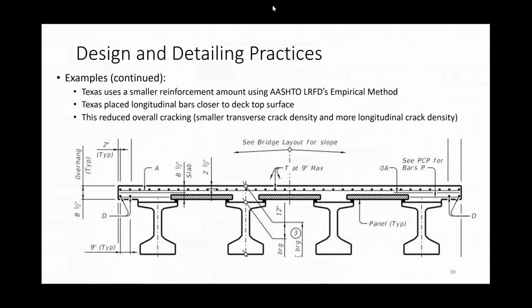All right, and then next up, Texas DOT again discussed how they reduced the amount of reinforcement as a method to reduce cracking. And that may sound counterintuitive, but their reasoning here is that if you have a smaller reinforcement amount, the corrosion products that build over time are going to be small, and that's going to create less pressure when they expand, and that's going to result in less cracking. So they switched to the empirical method, AASHTO's empirical method, to be able to get a smaller reinforcement amount as compared to the traditional method.